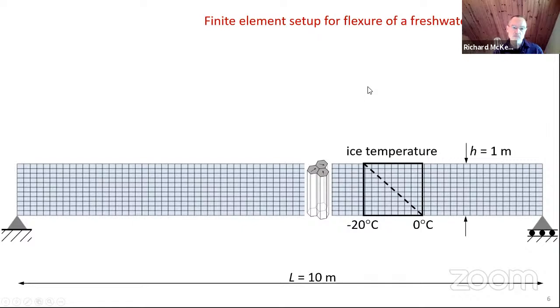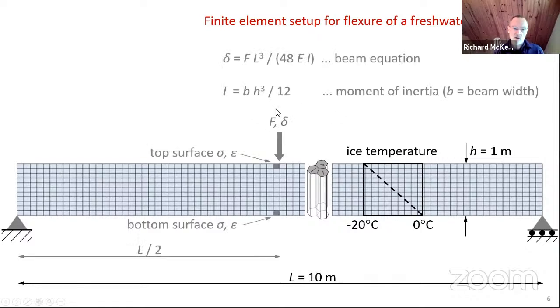For this simply supported beam, if loaded at the center, either using a force or applying a displacement, the beam equation applies, and that's the elastic beam equation. If one inverts that equation and looks at E as a function of your applied load and your displacement, that is what we use in this paper to get effective moduli. So we model the whole viscoelastic ice beam, and we look at the development of load and displacement at that point. The stiffness of the beam is effectively EI, where I is the moment of inertia of the beam.